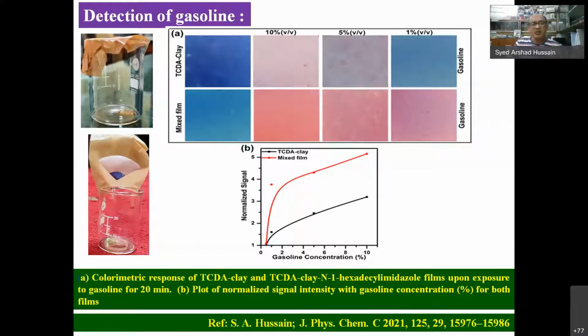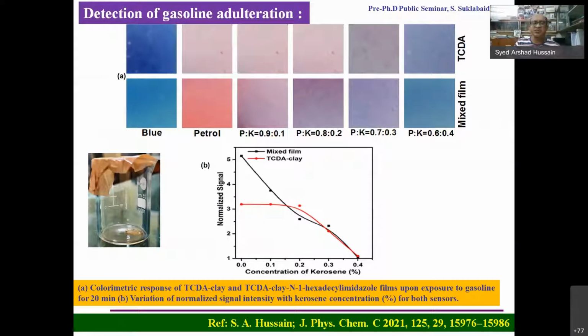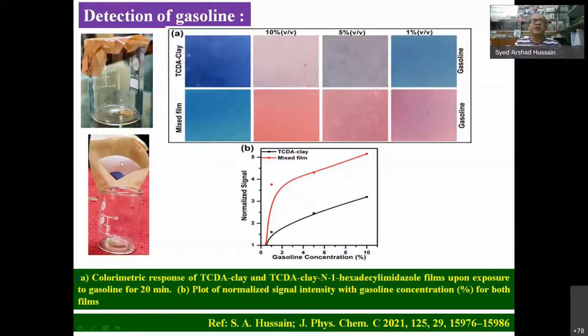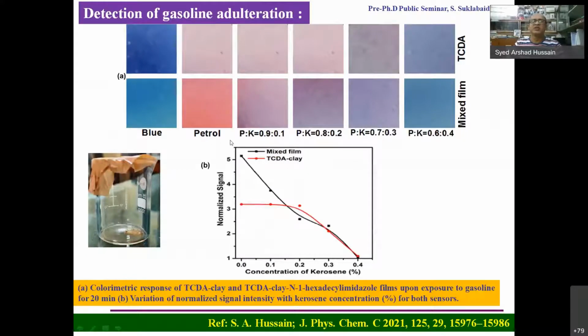Then we applied this material to check whether our gasoline is pure or it's adulterated with some other material. And normally in the locality they use kerosene to mix with the petrol, because kerosene is cheaper. So what we did initially, we observed that when we expose our blue phase film to petrol, it's converted to red. From here we optimized, most probably 10%. So for the 10% case, we mix kerosene at different ratios.